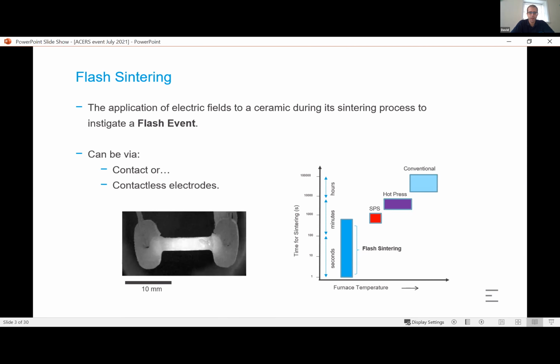So we tend to find that this simplification of this technology is quite prone to localization, and in the case of this rod that you're seeing being sintered here, you've got an over-sintered middle and an under-sintered outside where the thermal losses haven't done that. So at Lucideon, in order to make it scalable, we don't just think of it as a process that takes seconds, but almost seconds to minutes. And we've built software and electronic control systems to ensure that it's scalable and homogeneous sintering on real ceramic pieces.